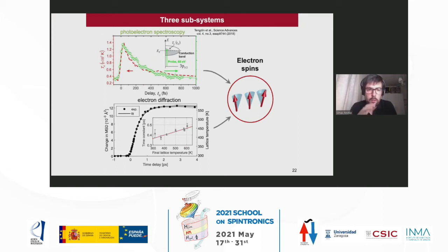What they see is that the lattice temperature has no peak, it just increases like an exponential, with a time constant of around half a picosecond. These two figures correspond to nickel, and the rising time of the electron temperature is similar to the decay time of the electron temperature, so they are related.